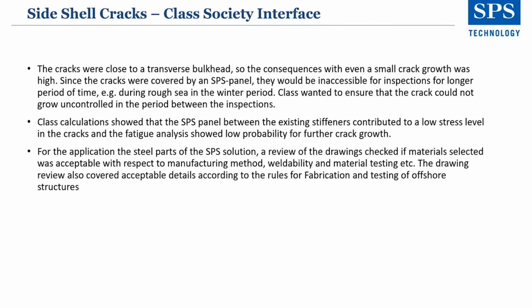So with the class society interface, they said the cracks were close to the transverse bulkhead, and the consequences with even a small crack growth was high. The cracks were covered by an SPS panel. Class wanted to ensure that the crack could not grow uncontrolled for a period between inspections. Class calculations showed that the SPS panel between the existing stiffeners contributed to low stress level in the cracks, and the fatigue analysis showed low probability of further crack growth.